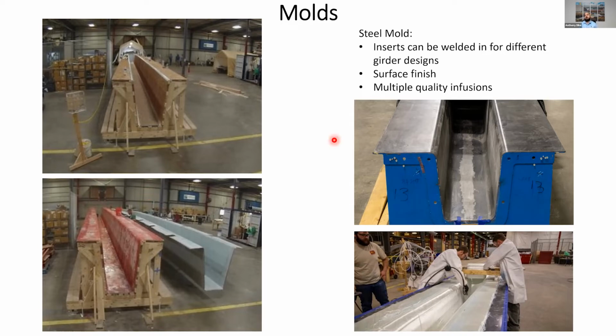And this is where we designed and ordered for fabrication a steel mold. Now this steel mold has been used for the other projects that I'll be talking about in a bit. Some of the advantages of having the steel mold is that we can weld inserts in the mold so that we can have different depths. The surface finish is superior to that of a gel coat, and steel molds can usually go up to about 100 or so infusions, sometimes more, depending on how well we maintain it. So that was the first step.